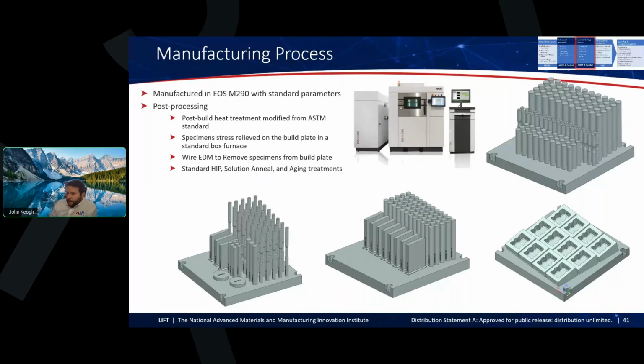It's additive manufacturing, but that's part of where the point tracking comes into play, because as you're passing your geometry model through your digital thread in the modeling and simulation space, you have to be able to flip that model over and understand that now the point's over here. Now it's going to be in a different environment, and there's going to be different heating curves and so on. So we ran that all the way through, followed all the ASTM methods, right? Stress relief, Wire EDM to remove specimens. We also hit solution anneal and aged, and then brought this into the physical test.